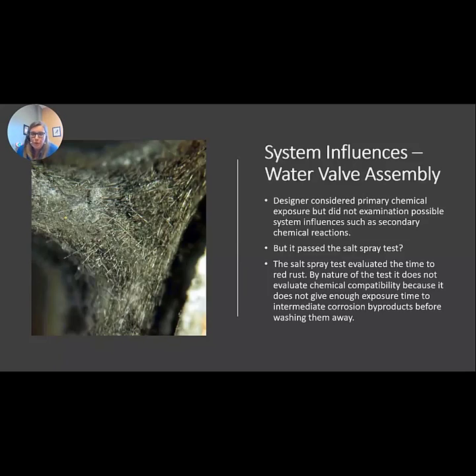So it's important to understand whenever you're doing product tests, you understand their purpose and their limitations. So in this case, the salt spray test is to evaluate the time it takes for the fasteners to get to red rust. It's not intended to evaluate the chemical compatibility of the corrosion products with the housing material. And actually performing that testing, you're constantly washing away the corrosion products. So it might take 168 hours to get to red rust. You're forming zinc chloride, but you're rinsing it away so quickly because it's continuously putting water on the part. So as fast as you form it, you're washing it away again, and it's not having time to dry and to get saturated and to actually attack the polymer.